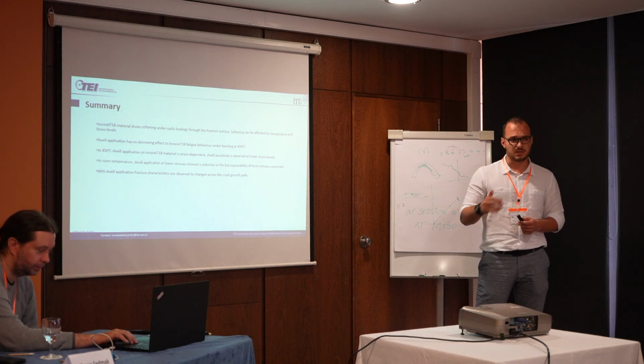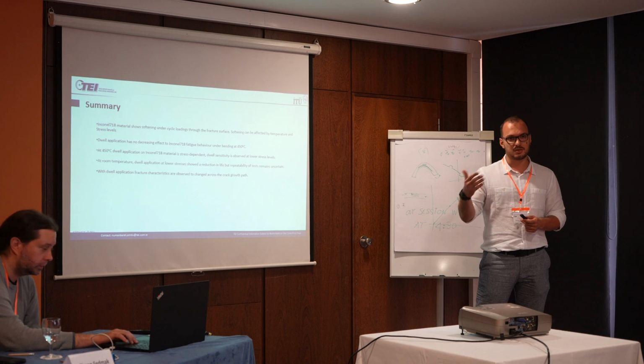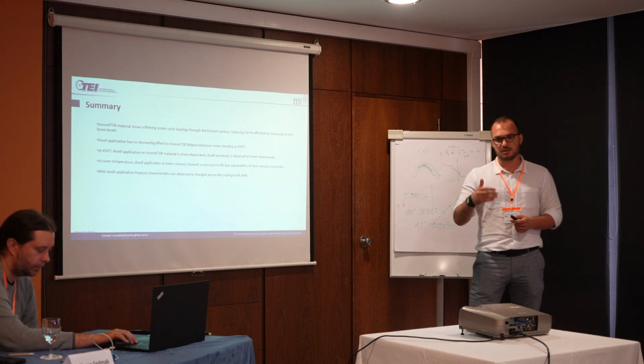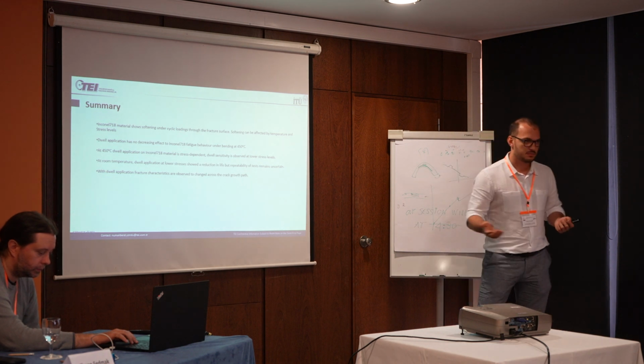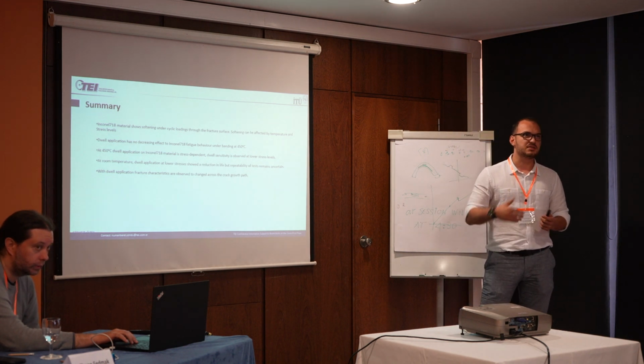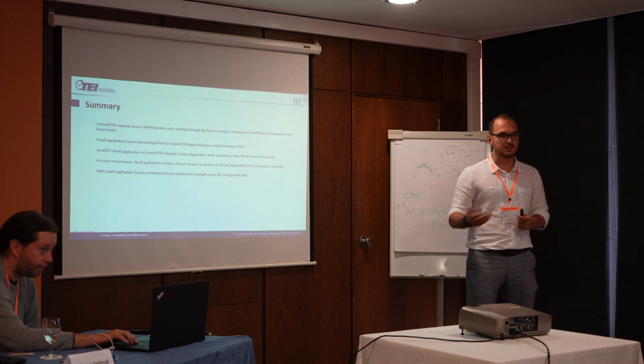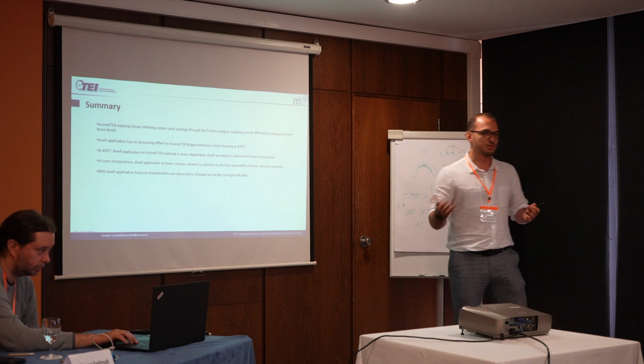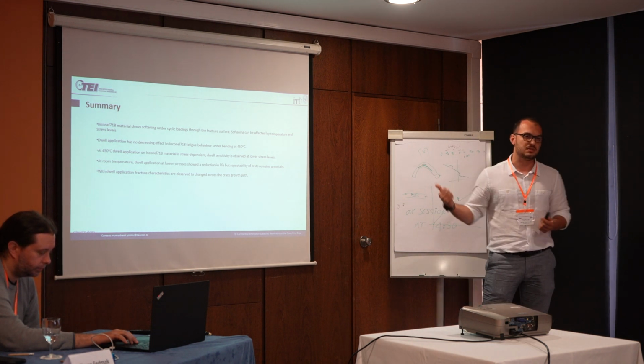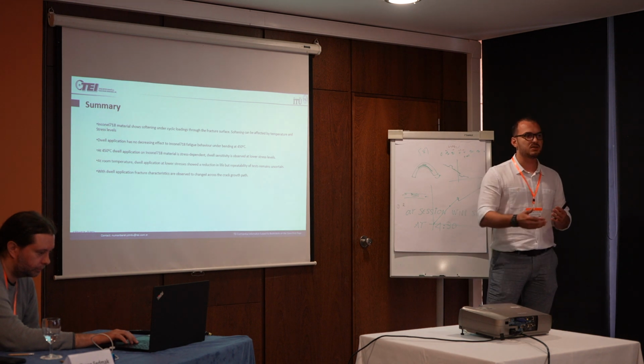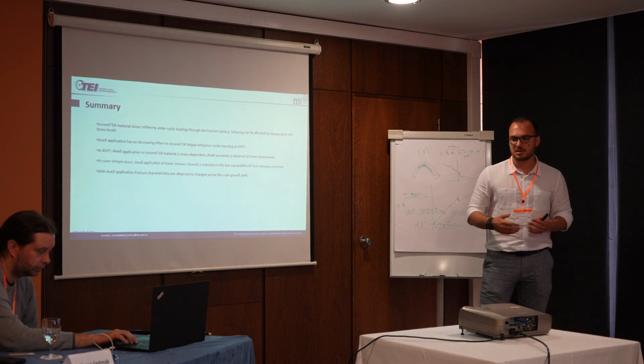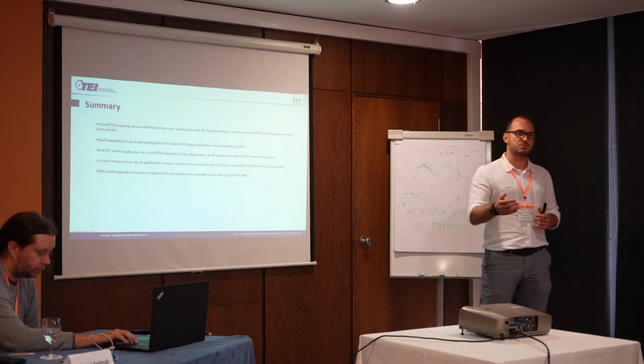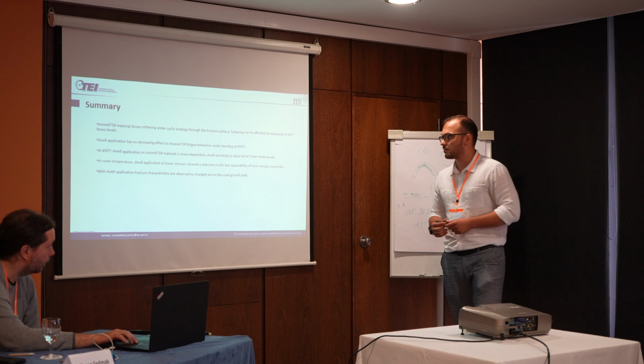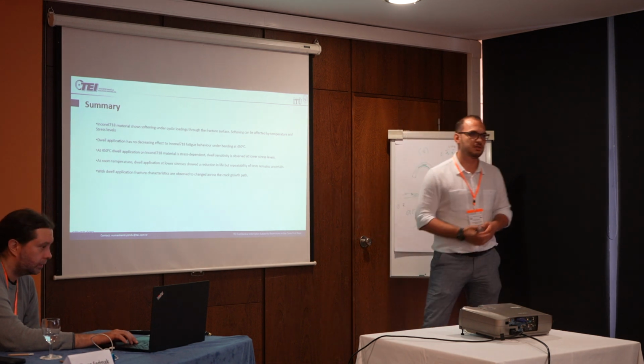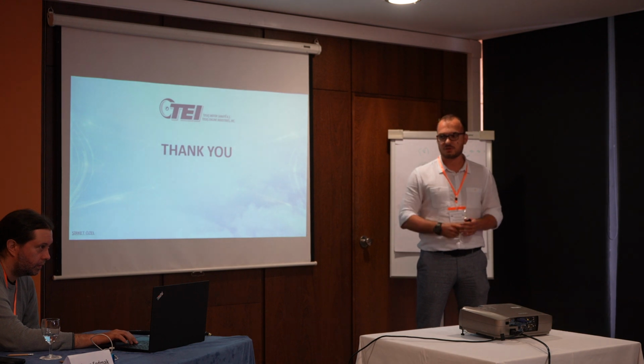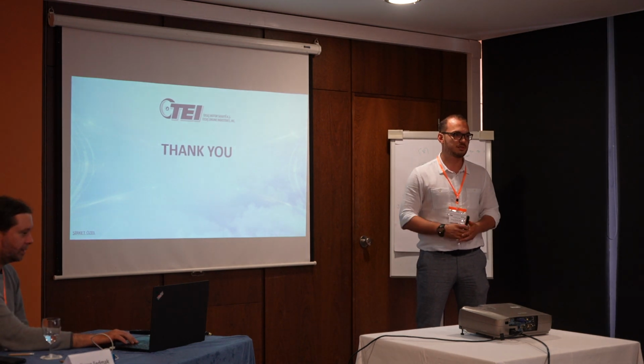in rotating bending condition, Inconel 718 at intermediate temperatures like 400-500 degrees seems to be not affected. Saying that the life increases with the dwell would be a really strong claim with this number of tests, but we can say that at bending conditions, Inconel 718 is a relatively conservative material in terms of dwell applications. This is my overall work. I thank you for your attention and am happy to hear some recommendations, comments.